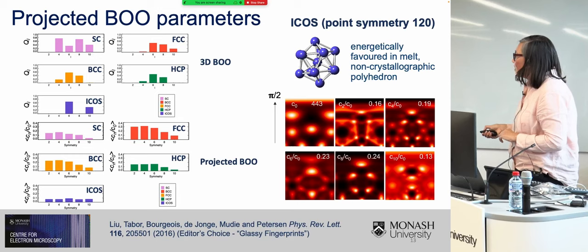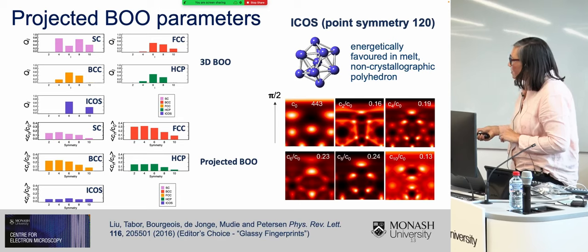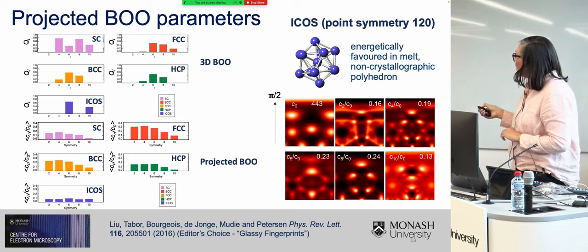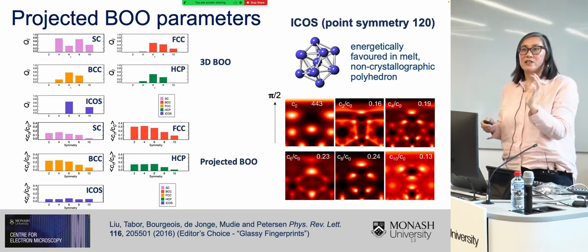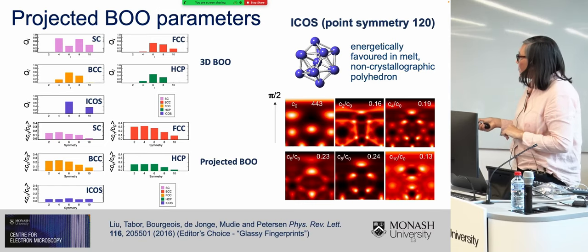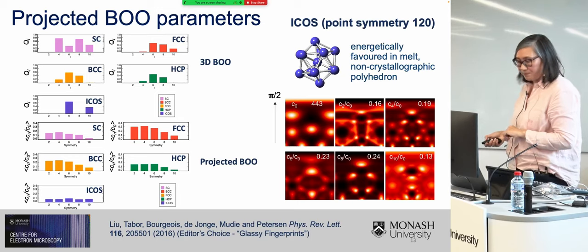significant differences between them. So for example, for the cubic clusters the highest magnitude is in the n equals 4 Fourier coefficient, compared to the hexagonal close-packed or icosahedral cluster, where the highest Fourier coefficient is n equals 6. And also the icosahedral cluster, which has the highest point symmetry. So that means that in virtually any direction you look down, you will see a symmetry. You can see that the distribution is somewhat flat, but peaked at n equals 6 and n equals 10.